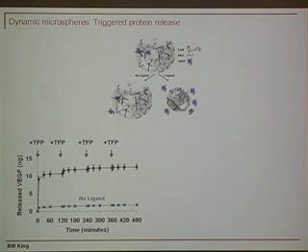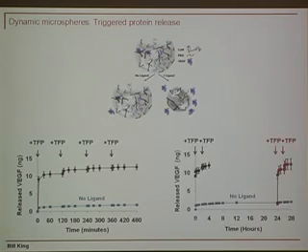So if we look at the comparison between VEGF release from these microspheres in the presence of no ligand compared to protein release in the presence of the trifluoperazine ligand, you can see that when TFP is added at time 0, there's a substantial change in the release rate. And then at subsequent times, if we keep adding TFP again and again and again, we do see additional bumps in the release curve, but that become less substantial over time, largely because we're depleting the protein from the network. So the initial release is quite a lot of the protein that's incorporated.